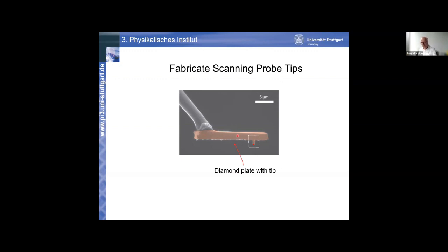So what you see here, this brownish thing, is a diamond plate. And you see a small protrusion here at the end. This is essentially a diamond waveguide. The diameter here is below a micrometer. Well, you see the length scale here. And at the end, I was pointing a red dot. This is actually where a single defect is sitting. And this diamond plate is mounted here on a stylus, and you can move it across the surface. It very much works like an atomic force microscope, if you like. And while moving, you can excite and read out the response of the defect by shining a laser from the top and collecting fluorescence at the top.